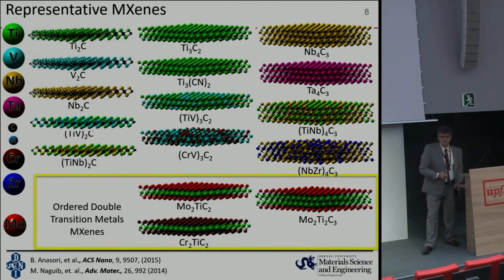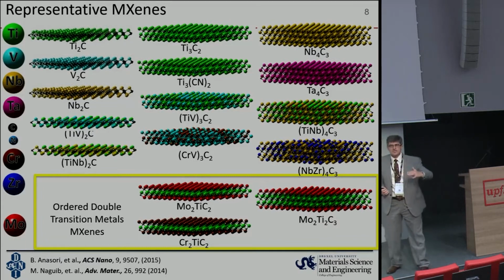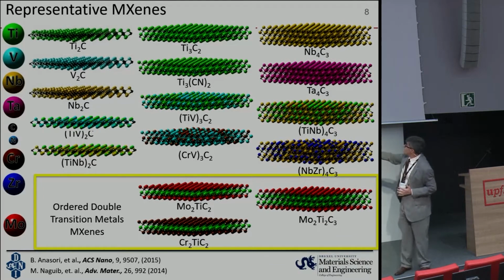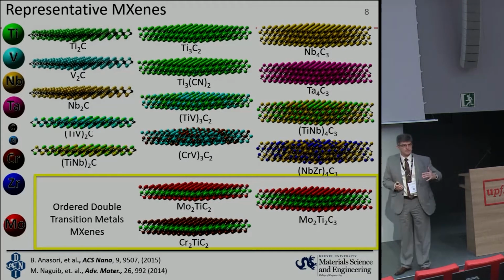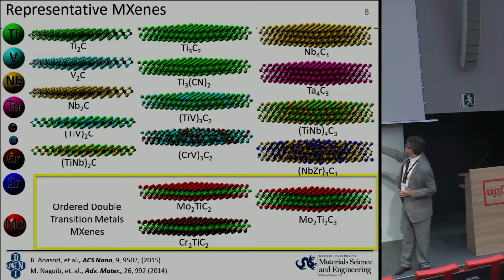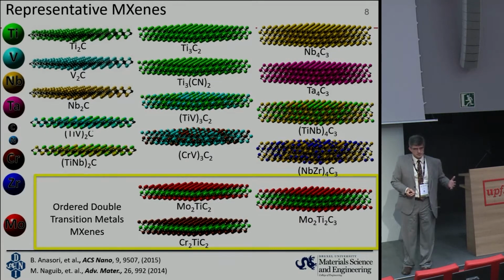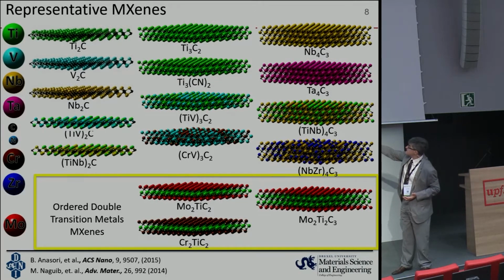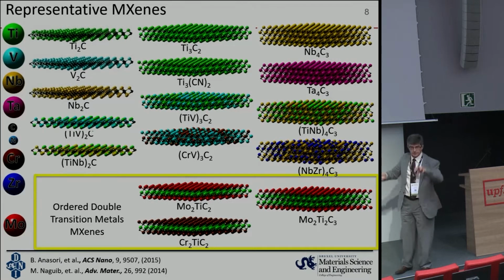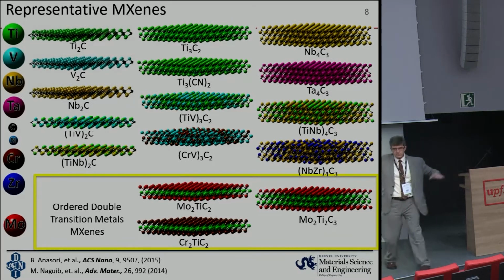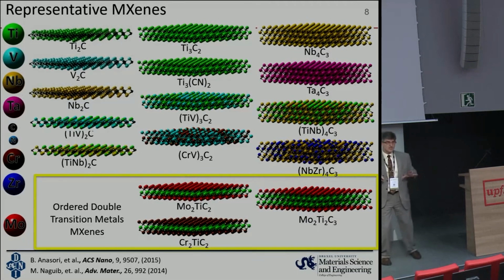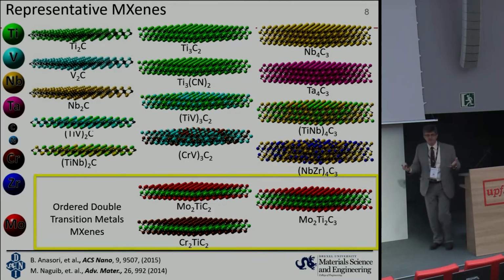And in 2015, we showed we can take atomic design to a next level. We can make a material in which one transition metal will be on the surface, controlling, for example, surface properties, catalytic properties of the material. Another transition metal will be in the middle, largely controlling electronic properties. For example, we can make Mo2TiC2 or Cr2TiC2, adding magnetic and other properties to these materials here. And of course, in these layers, we can again create a surface layer which will be mixed, in which we have, for example, catalyst atoms surrounded by some other atoms. So we can make a mix, for example, tungsten or moly surrounded by vanadium or other metal here. So there are huge opportunities for atomistic design here.